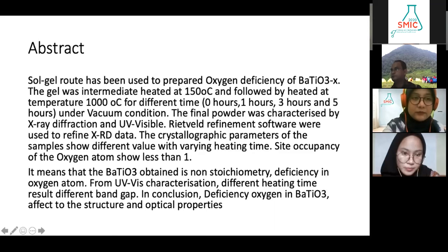The sol-gel route has been used to prepare oxygen deficiency BTO. The gel was intermediately heated at 150 degrees and followed by heating at 1000 degrees for various times under vacuum condition. The final powder was characterized with X-ray diffraction and UV-visible. Rietveld refinement software was used to refine XRD data, and the site occupancy for the oxygen atom showed less than 1. It means BTO was obtained as non-stoichiometric, with a deficiency in oxygen atoms.